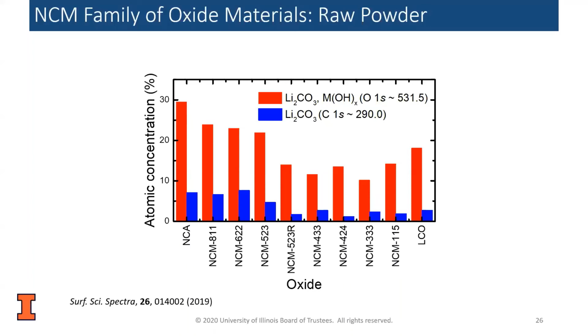Okay. All right. One more question about quantification of the species here. If we want to quantify the material loss, for example, manganese loss from the battery electrodes after cycling, wouldn't the XPS just give signal from the SEI? Or is there any mode that can selectively give signal from the electrode below the SEI so the quantification can be done? I guess the question is how well can you localize the information you are getting regarding the manganese loss in the material?